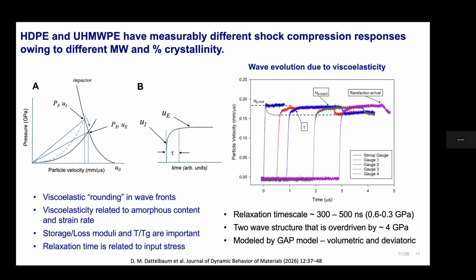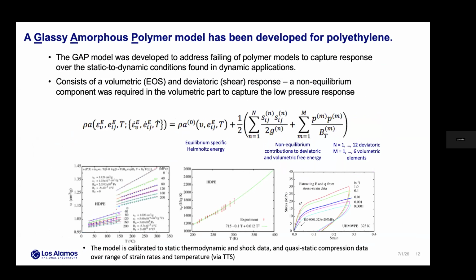I guess, in my view, just a commentary, is that much of the Hugoniot data for polymers at low pressure in the literature is incorrect in the sense that it's reported as a single wave structure, and you don't really know, because of the measurement technique and how they've analyzed the data, if they've reported the equilibrium or instantaneous states. So that's one thing on my to-do list working with my students: to put out a paper on viscoelastic relaxation times and actually do the formal reanalysis of some polymers in this regime.